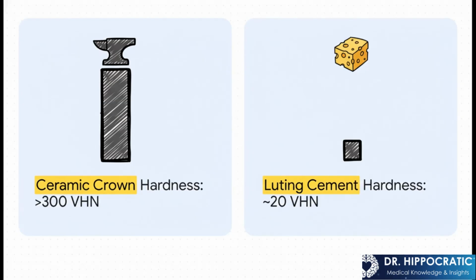But here is the catch. Just look at this comparison. The ceramic crown itself has a hardness value of over 300, but the resin cement, the lute that's holding it in place, its hardness is only about 20. That is a massive, massive difference. So we have this superhero crown being held in place by a much, much softer material, and this introduces a potential weak link in the chain.